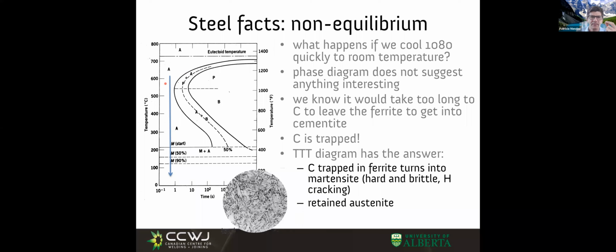But what happens if instead of quenching my piece of steel in molten salt, I quench it in water to room temperature? This happens very fast. Well, what happens in that case is super interesting. If I quench it very fast, like the way you quench swords in the movies - you make the sword, it's red hot, you're banging on it, and you put it in water - what is happening? What's happening is amazing.